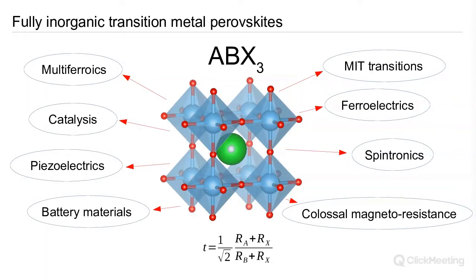I've just copied at the bottom here the so-called Goldschmidt tolerance factor, where essentially RA and RB are the radii of the A and B sites, and RX is the radius of the X site. So for systems where A is large and B is small, the tolerance factor goes greater than 1. In this case, this system tends to remain cubic. The B site can become underbonded, and we can see instabilities towards ferroelectricity, as we see in, for example, barium titanate, quite famously. Or when A is small and B is large, then the tolerance factor is less than 1.